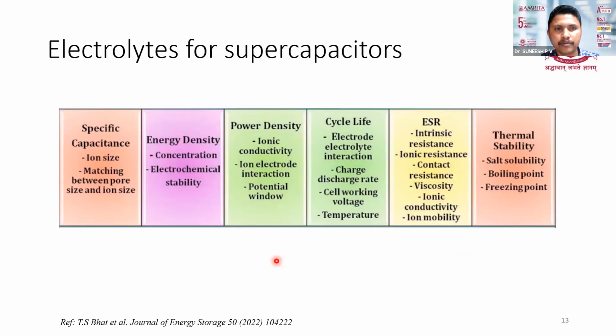cell system, electrode materials. But we can tune the electrolyte also to get more power delivery, as well as more energy stored in the device. And for that, there are different parameters to be looked at. One is the ionic size. Then the ion should go into the pores, means the ionic size should match with the pore dimension. Then the energy density of the capacitors can be affected by the concentration of the electrolyte that we are using, and also the electrochemical stability of those electrolytes.